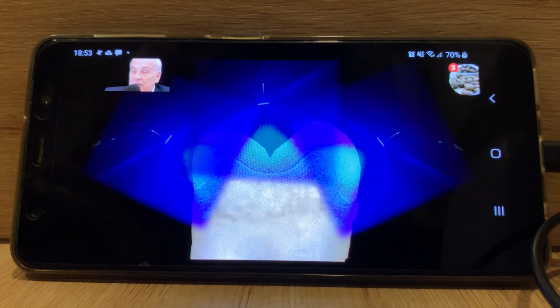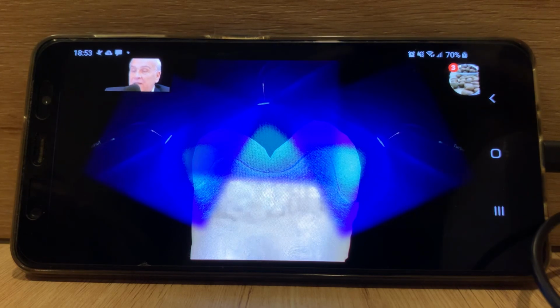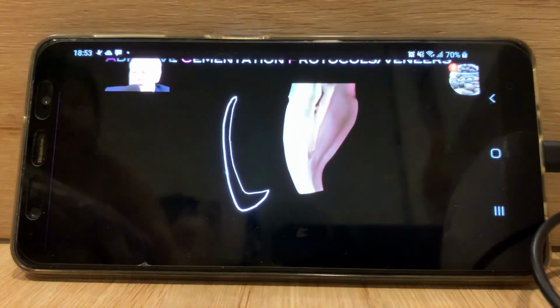which you should, remember that all dual cured materials are enhanced in terms of polymerization conversion by the light source. However, it's a good idea that you don't immediately hit it with the light. You let the self-cure part cure first. That could take up to a couple of minutes depending on the material, and then you would enhance it with the light cure. I normally use a total of about 1 minute on each side before the patient leaves, not all at once, but in parts. So that would be the tip of the day for that.